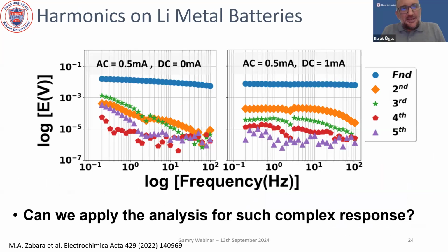So here is a battery that is being measured under two conditions. On the left-hand side, you are seeing DC 0, AC 0.5. And on the right-hand side, you're seeing DC 1, AC 0.5. Now, if you compare these two, the responses are pretty different. Let's start at the low frequency side. Remember, the green star is the third harmonic, and the orange square, let's call it, is the second harmonic.